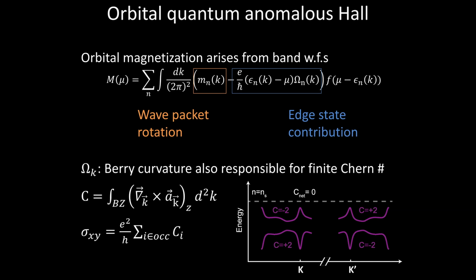Okay, and the interesting thing about an intrinsic orbital quantum anomalous Hall state, which is what we have, is that this wave packet self-rotation comes from the bulk bands. But even if you're inside an energy gap, so if you're inside a quantum anomalous Hall state, you just have the edge state, that edge state itself has equilibrium currents, which constitute some amount of magnetization.